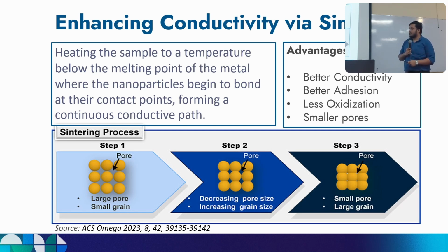The nanoparticles fuse together, and also the solvents are evaporated. So that results in better conductivity and better adhesion between the substrate and the nanoparticle ink. And also, since the metal is connected together very well, there is less ability to be oxidized. That means if there are metal oxides, the ability to conduct electricity reduces, the same as if there are organic things.